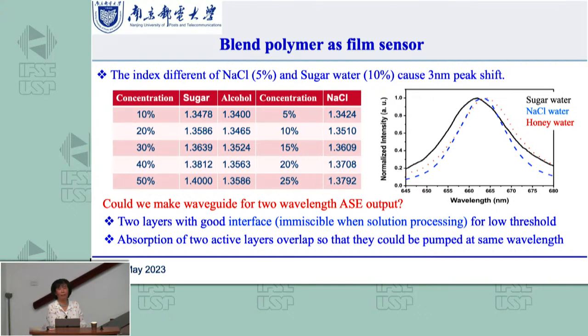Normally, if you make a material film, the materials both dissolve in solvents like toluene or chlorobenzene. When you put down the first layer, that's fine, but when you put down a second layer, the first layer will be dissolved by the second layer's solvent. That is something we had to solve. But we have an alcohol-soluble polymer material and a toluene-soluble material, so we can put these together to try this.